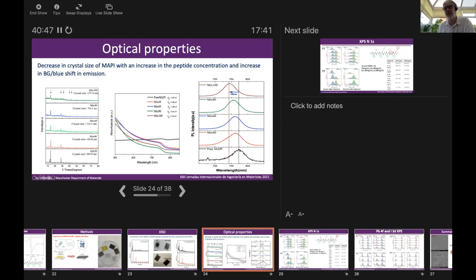which is suggesting that perhaps we are getting some quantum confinement. We see intermediate shifts at these lower peptide loadings, and we're not entirely clear because you can see they're quite broad. It's quite a broadening on this high energy, short wavelength side of the photoluminescence spectra. So again, this might suggest that we've got a mixture of encapsulated and non-encapsulated methylammonium lead iodide, which is giving rise to this kind of broadened peak that we observe here.